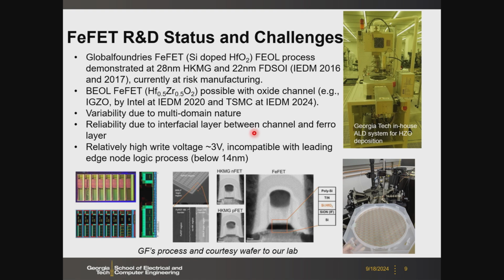That will create a lot of traps, and then especially during the cycling, you get a lot of electron trapping there. And then the last challenge is to move forward, let's say, because of this high write voltage, especially for the front end of line silicon channel, you have around 3 volts in terms of write voltage. This is higher than the typical logic core VDD, or even higher than the I/O voltage of advanced CMOS logic. So this will present some challenges in terms of the circuit design. We have to have a specialized on-chip charge pump circuit to drive this high voltage moving forward.